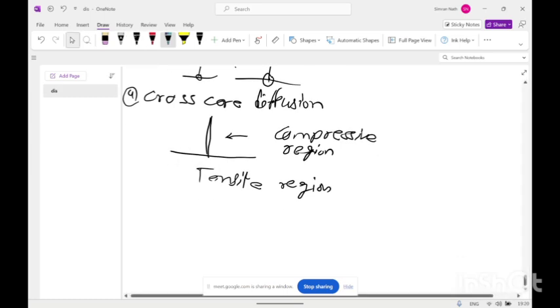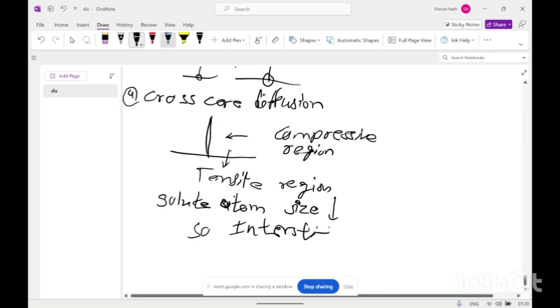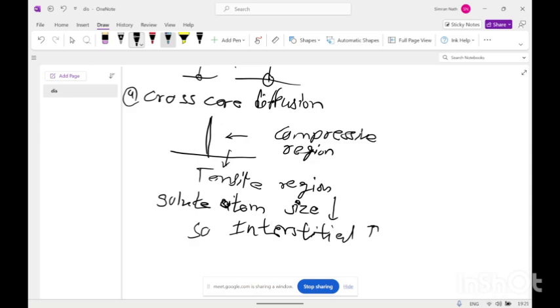So what will be the case when the atom diffuses from the compressive to the tensile region or tensile to compressive? If the size of the solute atom is large, it will create more strain field in the compressive region, so it will shift from the compressive to the tensile region. If the solute atom size is small, then the solute atom will diffuse from the tensile region to the compressive region. In the case of interstitials also, if the atom size is higher, it will diffuse from compressive to tensile, and if the atom size is small, it will diffuse from tensile to compressive region.